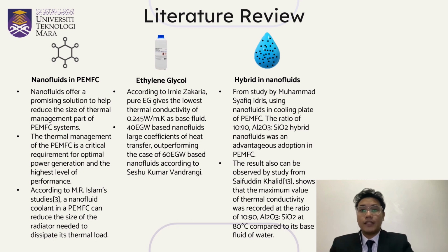The result of the study shows that Al2O3 with 40 ethylene glycol, 60 water nanofluids tend to be associated with significant heat transfer coefficient. From the study by Muhammad Shafiq Idris, using nanofluids in the cooling plate of PEMFC, the ratio of 10-90 of Al2O3 SiO2 hybrid nanofluids was an advantageous adoption in PEMFC. The highest enhancement was given by the hybrid 10-90 of Al2O3 SiO2 with 5.52% enhancement as compared to the base